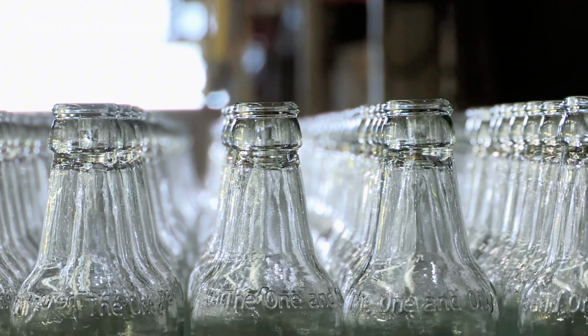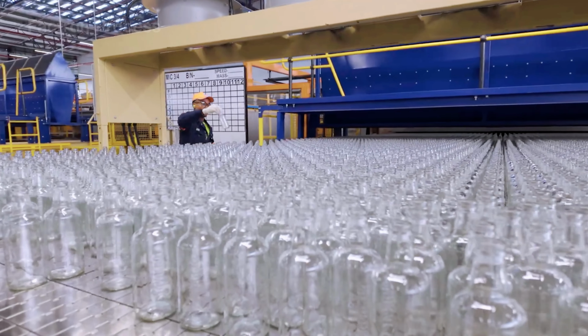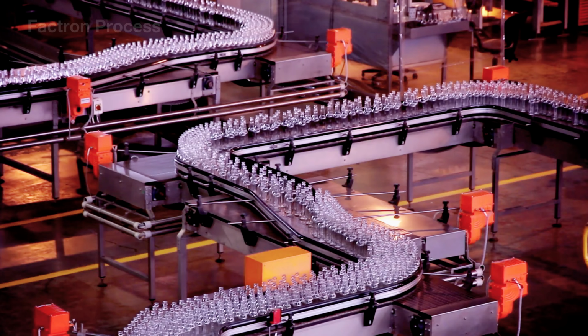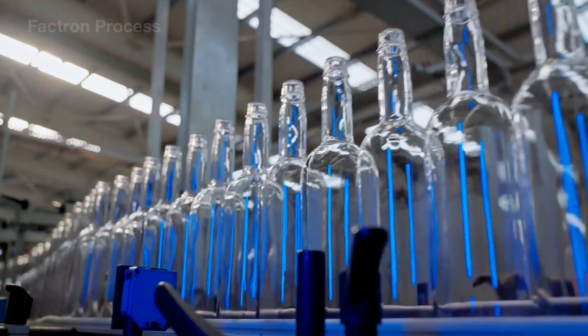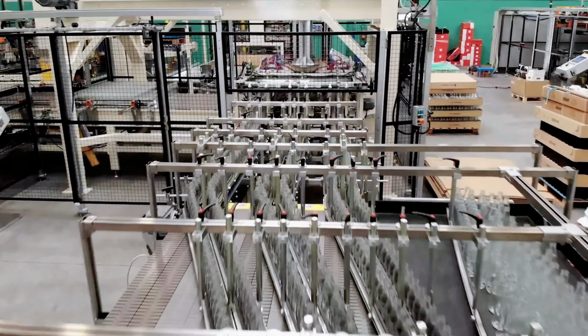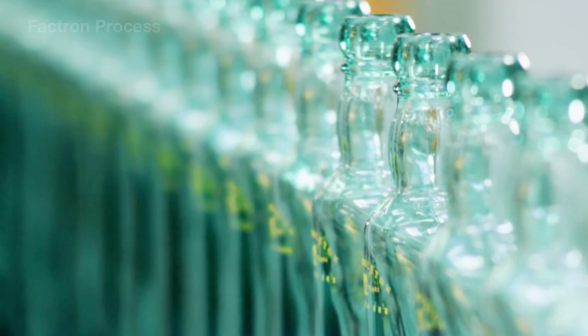Inside the annealing lehr, the temperature is controlled by zones. The bottles move slowly from the hot zone to the cooler zone, so the internal structure becomes more stable. This is a quiet step, but it determines the true strength of the product.